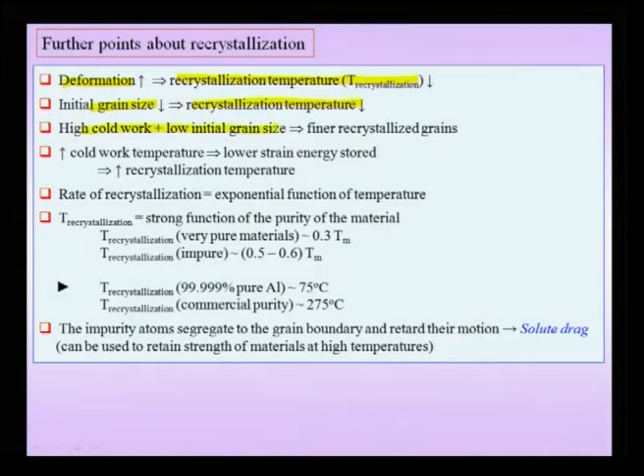That means that if you have a high amount of cold work, that means a higher amount of deformation, along with a low initial grain size, the finer will be the final recrystallized grains. Therefore, if I am interested in producing a fine crystallite size, then I need to start, of course, with a lower grain size and I have to do a high amount of cold work.